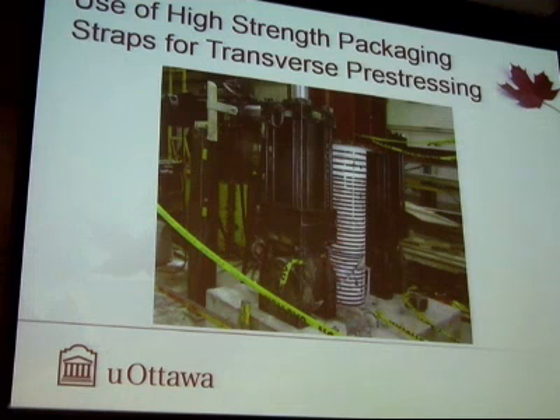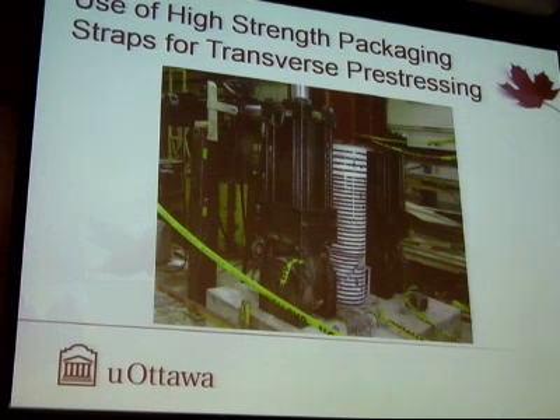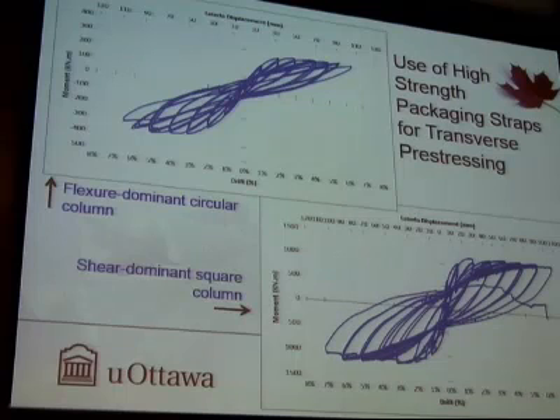Here you're looking at what used to be a rectangular column. Now it's an elliptical shape, retrofitted with transverse packaging straps, pre-stressed up to approximately 30% of the capacity and allowing some further expansion during earthquake. And you see improvements in hysteretic relationships as you compare those against unretrofitted columns. In the top left corner, we have a flexure dominant circular column, and then the bottom right corner was a shear dominant column. Because of this transverse pre-stressing, the mode of behavior changed from a brittle shear mode to a ductile flexural mode.